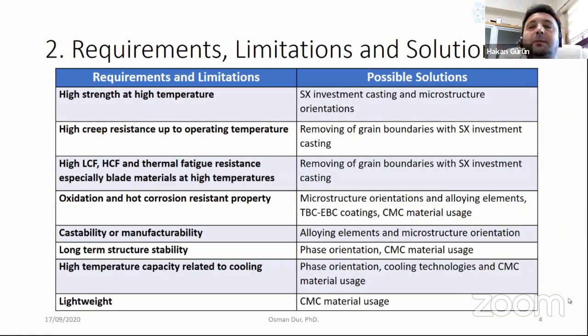These are the requirements, limitations, and possible solutions for blade and vane materials. High strength at high temperature is the most important issue for these parts, and single crystal casting is a solution for high temperature usage, with elimination of grain boundaries and their problems. Creep and fatigue resistance are again related to the removal of grain boundaries. Oxidation and corrosion resistance can be handled by TBC and EBC coatings and ceramic matrix composite usage.